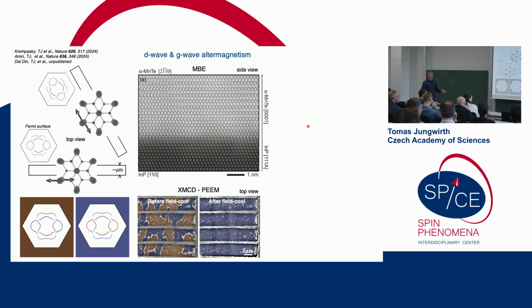And so if you want to see such a spin polarization in a spin-resolved photoemission experiment, the first and most important thing you have to have is a single domain sample. Single domain in terms of crystal domains, but also in terms of the time reverse domains. You have to have one such that you can detect the net spin polarization. So here is how our experimentalists do this. The previous experiment was very simple, I needed just one slide, but it took them 1.5 years to complete this experiment. This is a 2 years effort, again, on 2 slides.